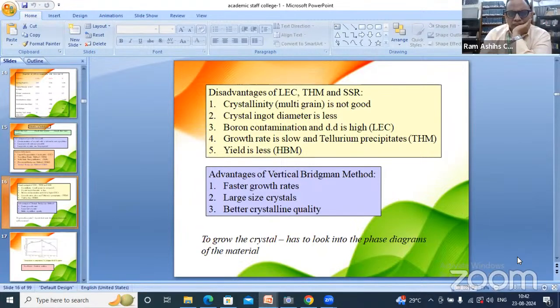For the other methods for CZT, LEC, traveling heater method, and SSR method, crystalline quality is not good. Crystal ingot diameter is less. In the Czochralski method, the boron contamination is very high, the growth rate is very slow, and tellurium precipitate is there. And the horizontal Bridgman method gives half the yield because of the diameter of the crystal. Advantages of vertical Bridgman are the faster growth rate, larger size crystals, and better crystalline quality.